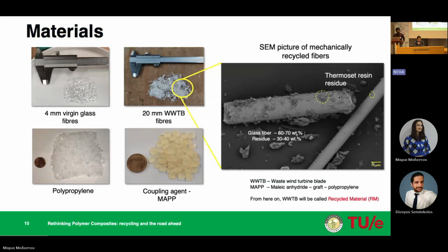So, firstly, I would like to talk about the materials itself. As I've already mentioned, this is the glass fiber which is coming out of wind turbine blade waste. As you can see here, the glass fiber has more thermoset residue on it, which becomes a huge problem while reprocessing it. So in my research, I've made use of a simple thermoplastic matrix, that is polypropylene, and I have also used a coupling agent called maleic anhydride polypropylene to address the problem of interfacial adhesion.